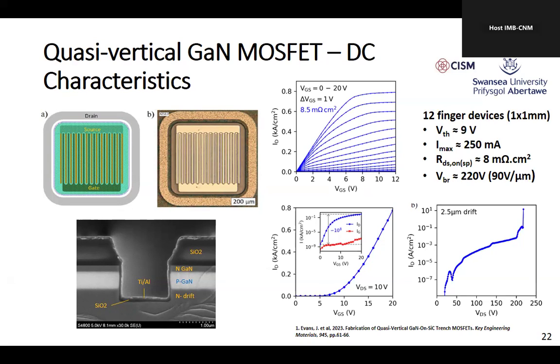We had a nice transfer characteristic, with a threshold voltage a little bit high, and that's because it was quite difficult to control the P-body doping. We also noticed that the threshold voltage was quite unstable with temperature, because we think we're activating more of these GaN dopants, or ionizing, I should say, as we increase the temperature. But as a first attempt, this is a really nice device. We've got a threshold voltage of 9 volts, a very nice specific on-state resistance and a reasonable breakdown voltage, giving us 90 volts per micron. So it's a very nice first attempt.